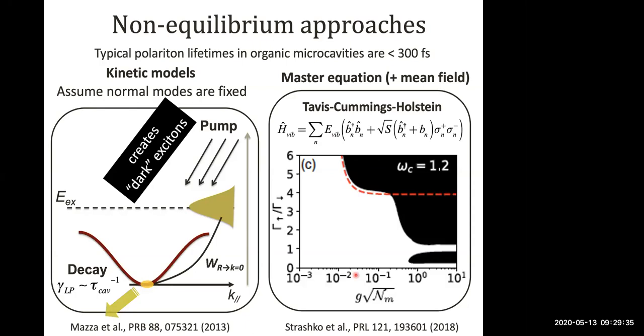The overarching conclusion from that work is that polariton lasing allows you to obtain coherent light emission at low thresholds, particularly in regions where you have high absorption, where photon lasing would be greatly inhibited. This is an example in a regime of positive detuning. Omega C is the cavity frequency, and here the exciton frequency is equal to 1. This red line shows the phase boundary for conventional lasing, and you can see that you have regimes of polariton lasing at thresholds, in terms of pump power, much lower than that necessary for photon lasing. So this is a nice perspective. This is all single photon mode, but this theory was very recently extended to the multimode case.